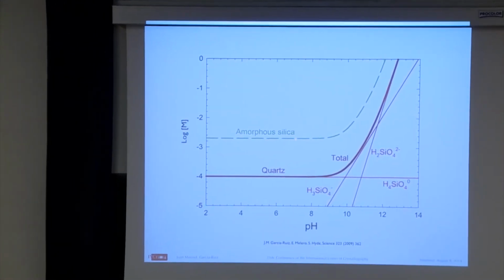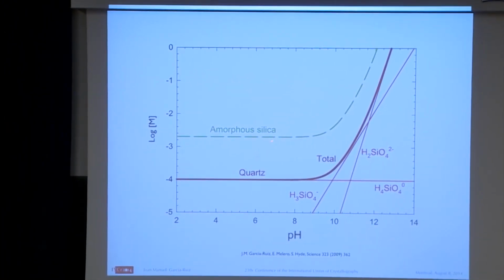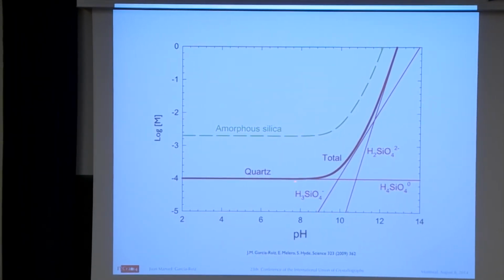The chemistry of this, because I think this is interesting. This is the solubility of silica as a function of pH. This is the key point here. Above pH 8.3, the solubility increases dramatically because of the first and second deprotonation of the silicic acid, right? So here there is a very large variation of solubility with pH.